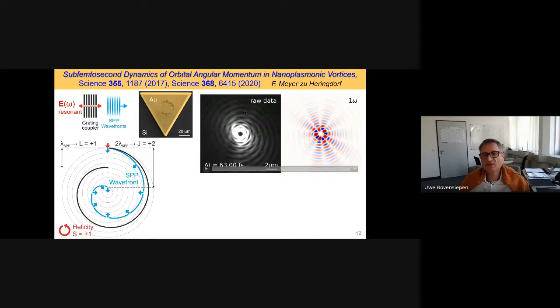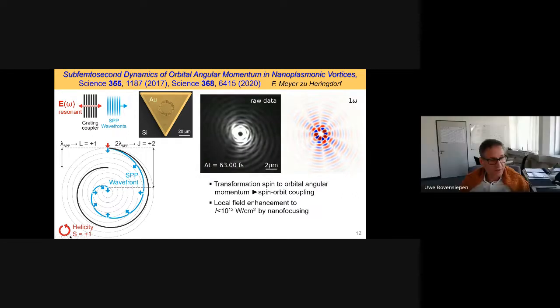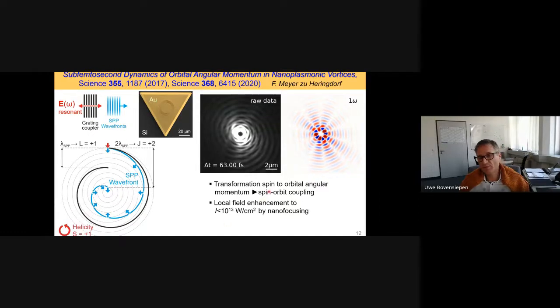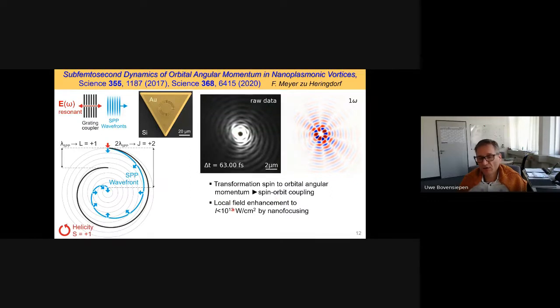And you can see here the microscopy image of a photoelectron emission microscope. And with this movie, you now see exactly what I motivated before. So here you see the real data within the optical cycle, and on the right you see a Fourier transform of the first harmonic. So why is this relevant? Well, just think about fundamental problems like spin-orbit coupling in condensed matter. Here, with such an approach where you see the transformation from spin to orbital angular momentum, you can really investigate the timescales related to this. Another aspect of this work is the local field enhancement that you can generate here locally, which goes up to 10 to the 13 watts per square centimeter intensity by such nanofocusing.